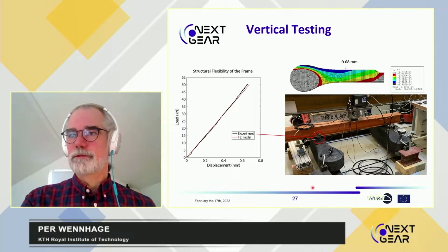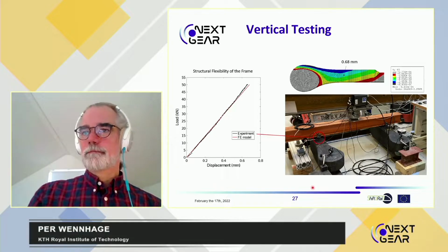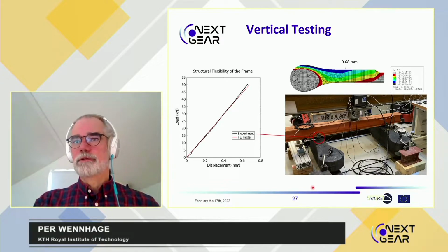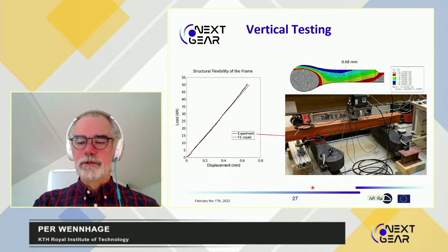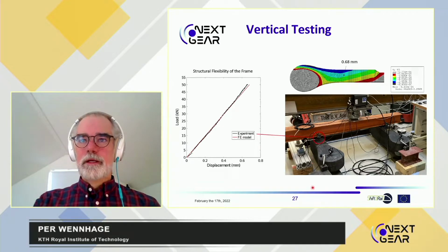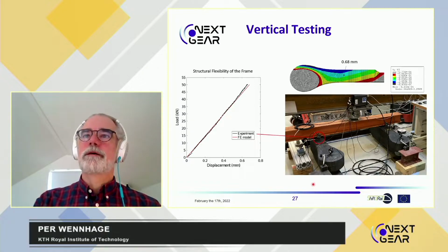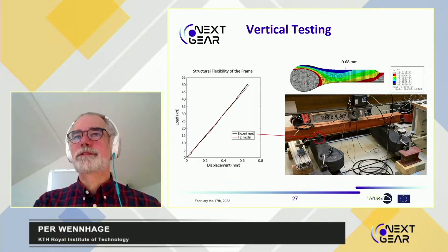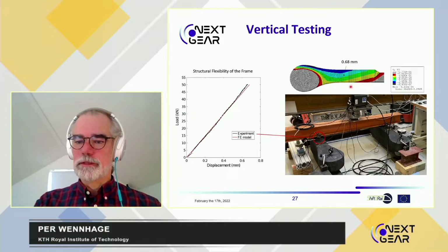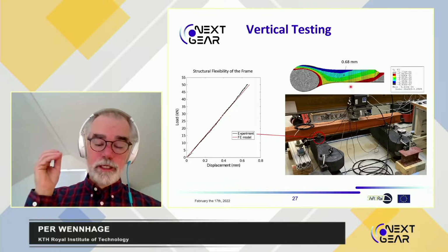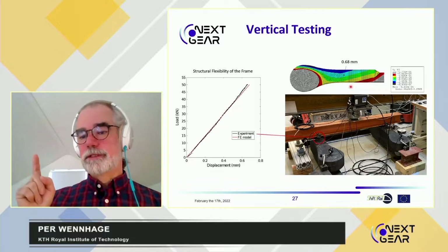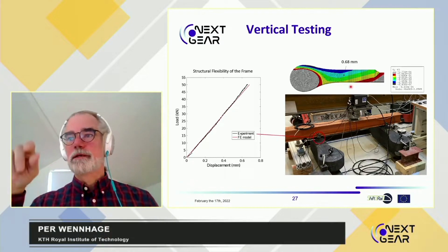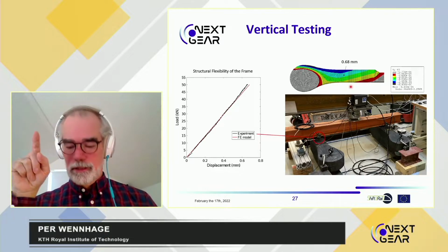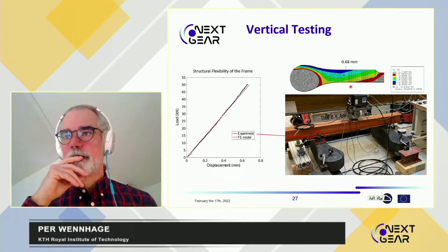This is for vertical testing. So we have a load point at the middle of the orange colored beam there that will press down with a hydraulic cylinder. And then we measure the displacement at a lot of different positions. And we pick out the same position in the finite element models where we actually make a finite element model of this particular test. In that way, we can get a fair comparison.